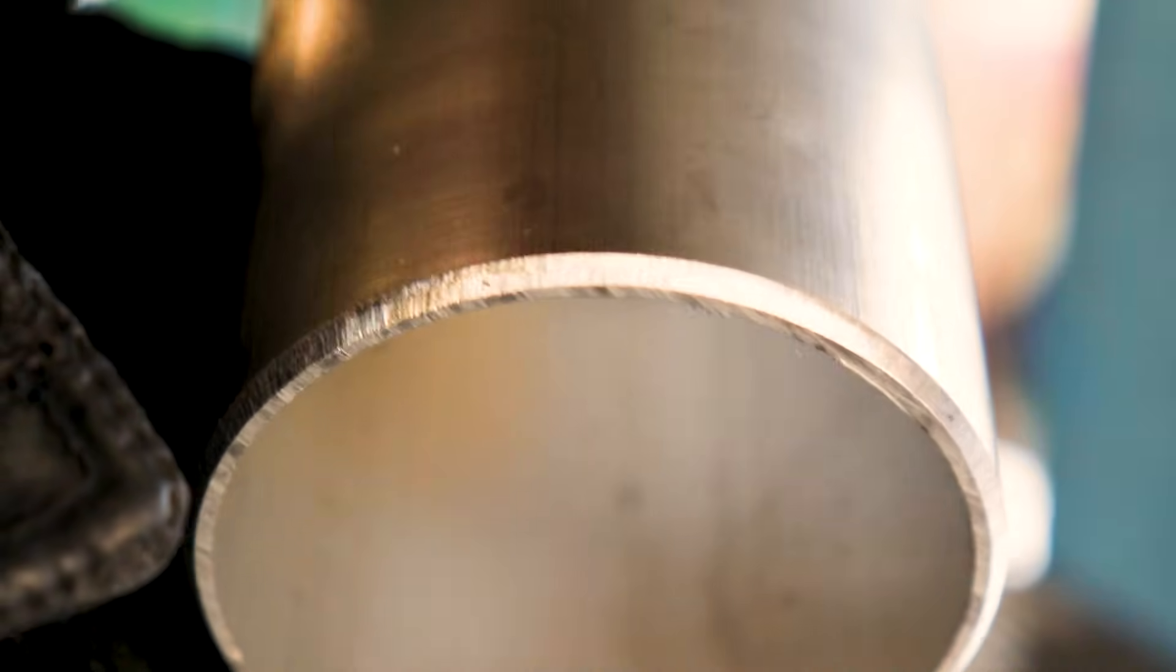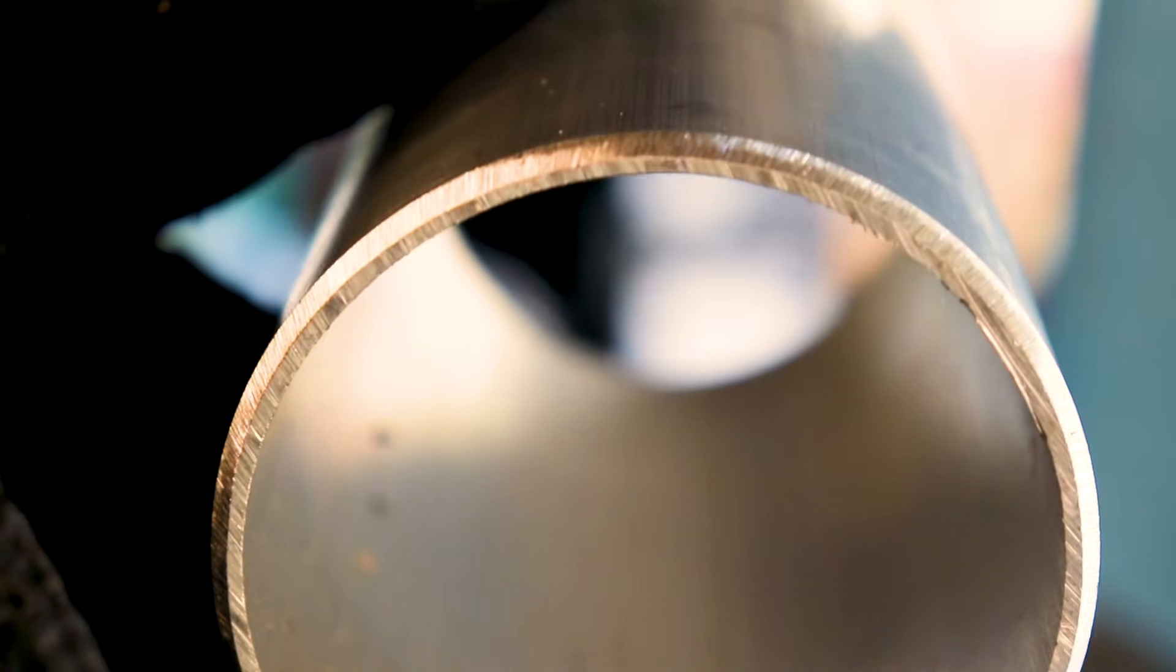I'll grind it down to where there's only about a sixteenth inch land and that's what I use for every type of aluminum pipe even if it's schedule 80.